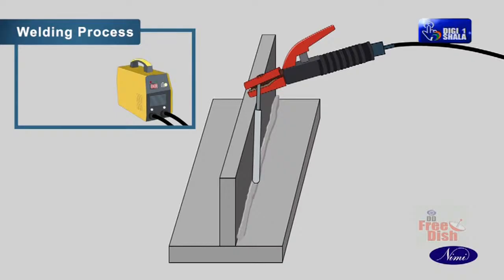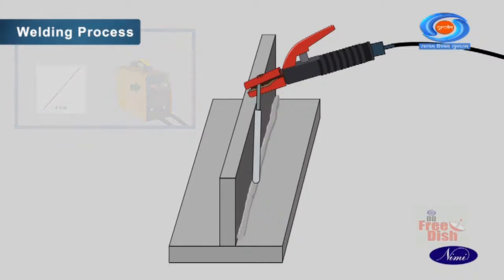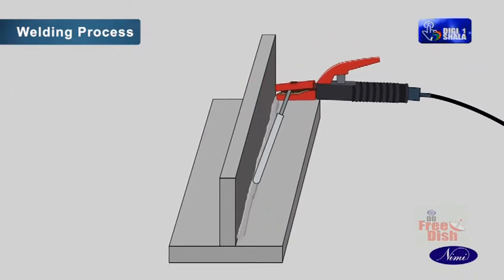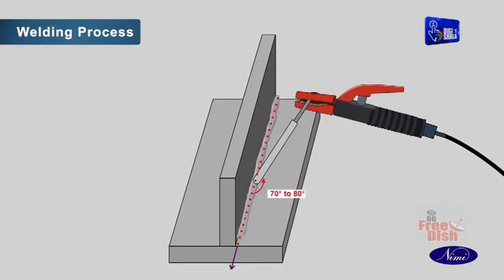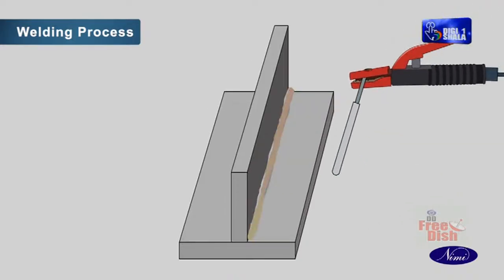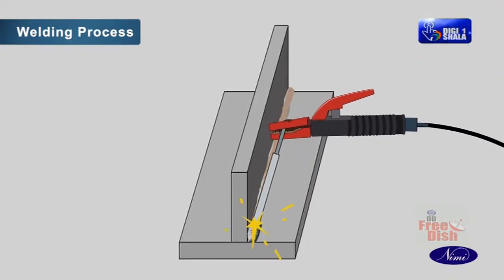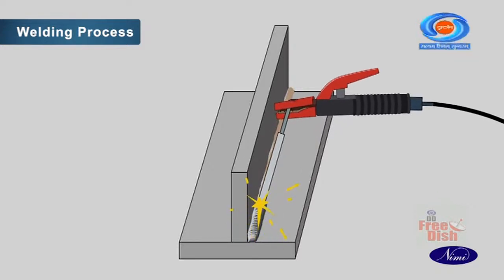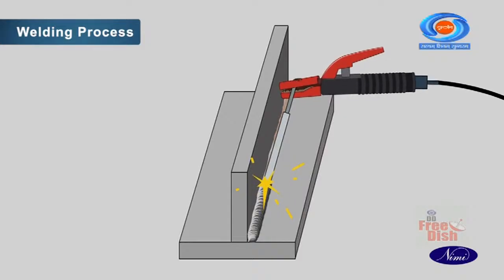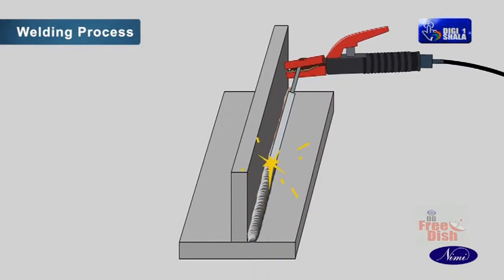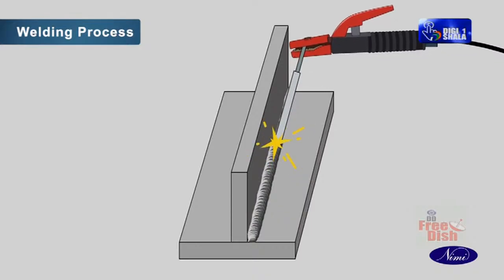Deposit the third and final run with a 4 mm dia electrode and 160 amps welding current. Angle of the electrode to the line of weld is 70 degrees to 80 degrees and 40 degrees to 50 degrees on both plates. The third run has to be deposited in such a way that the bead covers partly the root run and the second run and partly the vertical plate. There should not be a gap at the bottom toe line of the third run in order to maintain necessary throat thickness. If two-pass technique is adopted, the second run should be done in a weaving motion.